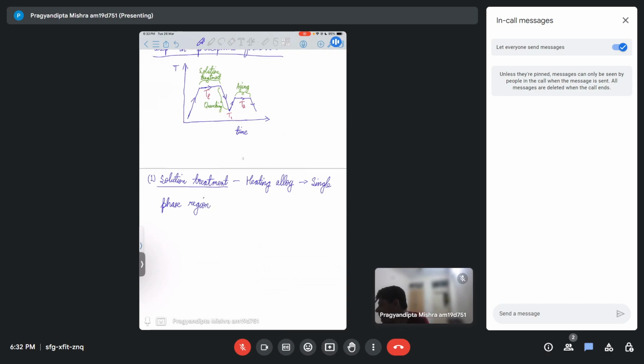So heating the alloy and holding it at a particular temperature, you will be seeing a single phase region, and that will dissolve any precipitate or phase present. Anything that is present will get dissolved because the temperature is high. Now the solubility has increased, so anything can get dissolved.